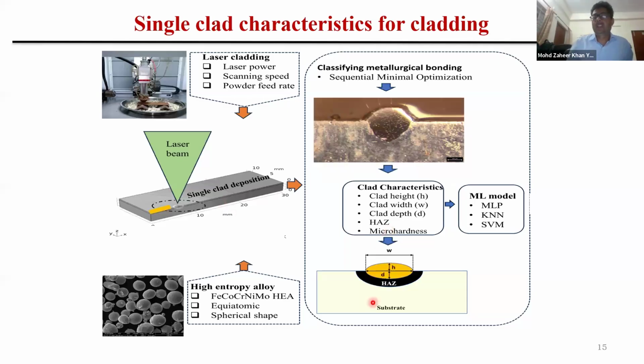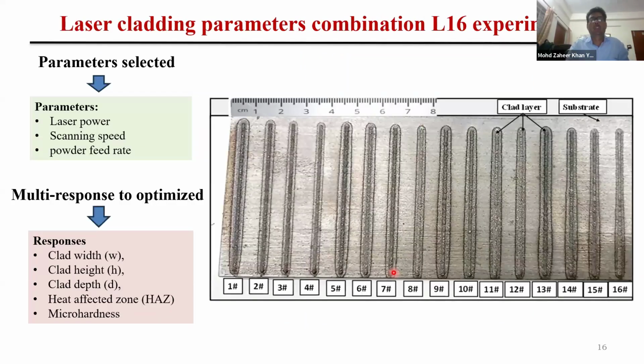should be noticed. The important characteristics are: what is the depth of penetration or depth of melting that has taken place, what is the height of reinforcement that is created, that is basically corresponding to the thickness of the clad layer that has been obtained, then what is the width of the clad layer, what is the extent of damage that has been done to the substrate in the form of a heat affected zone, and ultimately how this is performing. So microhardness of the bead can be taken as one of the parameters. So these types of experiments are performed.